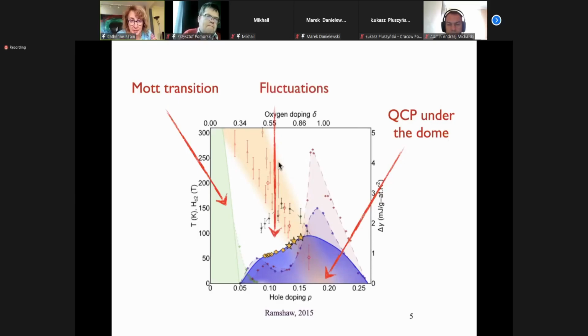And last but not least, the pseudogap might just be due to some fluctuations. It's basically the part I prefer. As I said, it's not exclusive. If you reach a metal insulator transition, particles will localize, namely the phase will start to fluctuate by the Heisenberg uncertainty principle. It's a very simple quantum mechanical statement. So you'll get a lot of fluctuations in the proximity to a Mott insulator. And moreover, it's a very anisotropic material, so you might have quantum fluctuations due to the reduction of dimension.